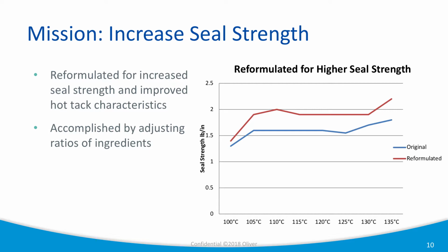The reformulation, we were tracking closer to 2 pounds. So we were able to get a higher output by just changing the ratios of the components, and that was a big win for the medical device manufacturer. We also did some things to improve hot tack strength.